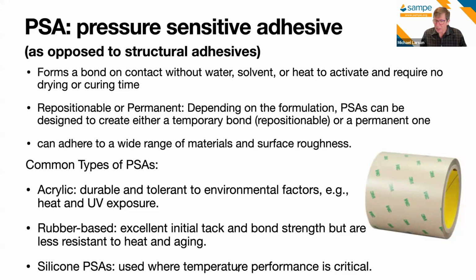The three most common that we use in design structural applications are acrylic. These tend to be durable and tolerant to environmental factors. Rubber-based, and these typically give us an initial tack that is very strong, but less resistant when it comes to heat and aging. A lot of early internal components, the interior of automobiles, used rubber-based ones that turned out to not hold up over time.